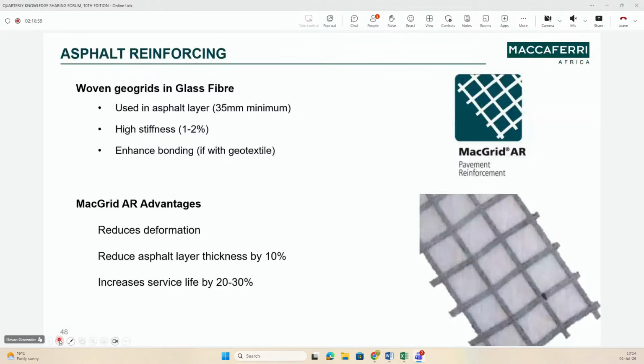There is enhanced bonding if it is with a geotextile, because it is impregnated with the bitumen. The advantage is that it reduces deformation, reduces asphalt layer thicknesses by 10%, and increases the service life by 20 to 30%.